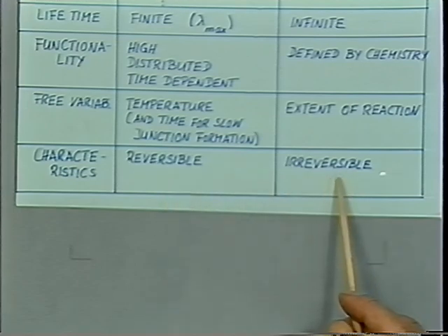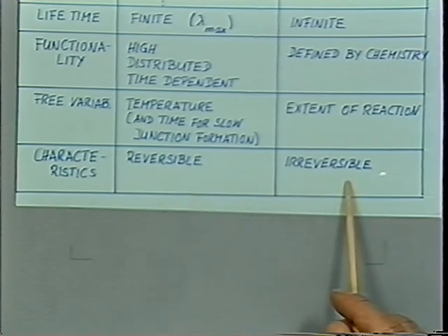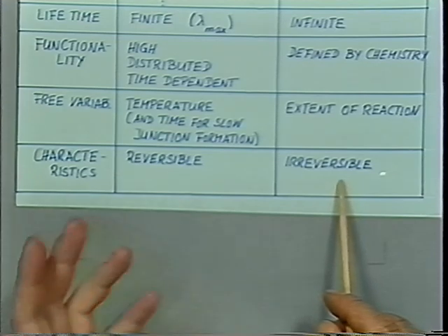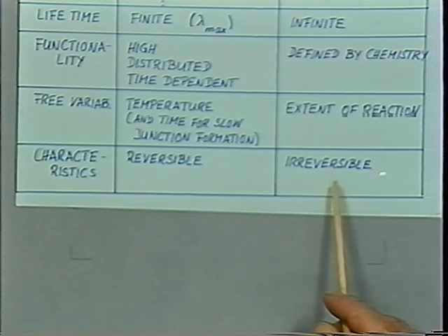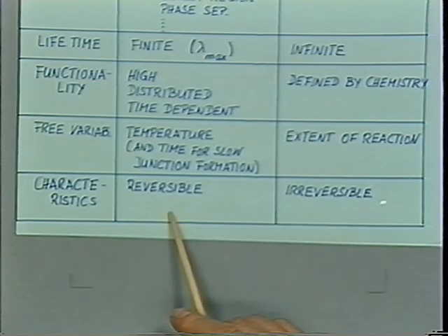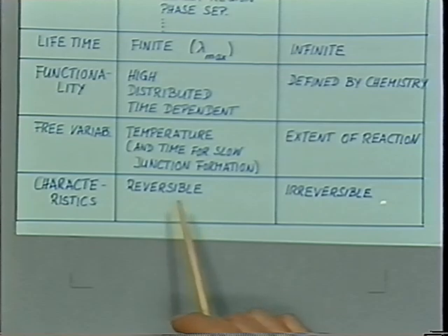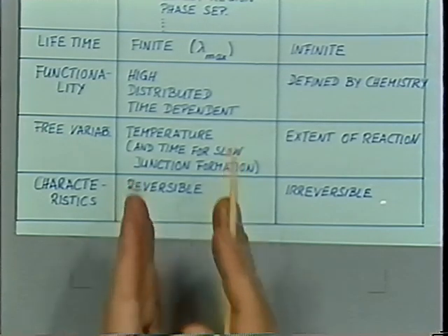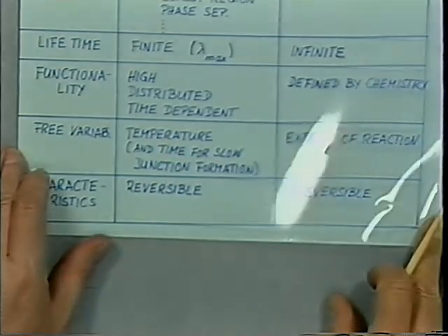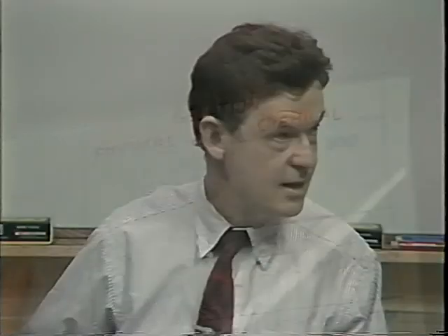It's nice that you can stop the reaction in chemical gels and produce well-defined samples which you can test over wide temperature ranges, and you won't change the connectivity in those gels. So time temperature superposition is applicable, but due to the reversibility, we cannot do time temperature superposition in physical gels. So naturally, those systems will only be understood in very narrow windows, while here in chemical gelation, we will have data over wide temperature windows. You will see that's the characteristic of whatever we will be doing in this case.